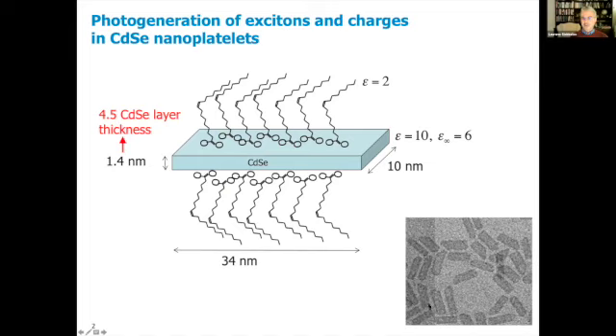And here you see TEM images. They have a length of about 34 nanometers and a width of about 10 nanometers. And they have a static dielectric constant of 10. But we have dissolved them in hexane. That's possible due to these oleic acid ligands on the surface, and that has a low dielectric permittivity of only 2.